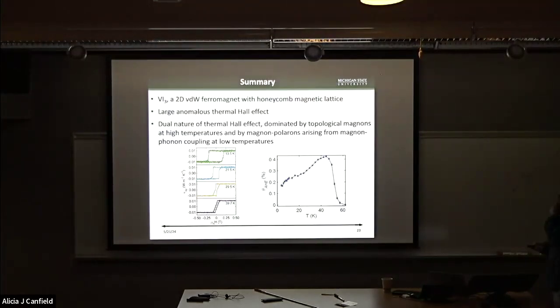Last year we tried to co-align 1,000 pieces of vanadium triiodide inside the glove box. My students spent three, four weeks, something like that. We spent four days trying to do the experiments on the spectrometer. Didn't see anything. We did not see anything, but it's just because the sample mosaic is too big, way too large. Because again, the students need to co-align the samples inside the glove box under the microscope. It turns out that the quality of the co-aligned sample was just too bad. So we did not see anything.